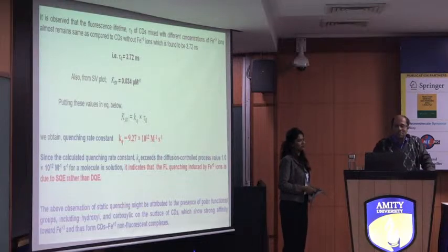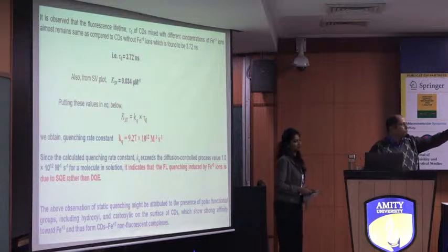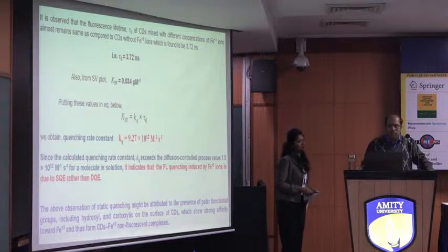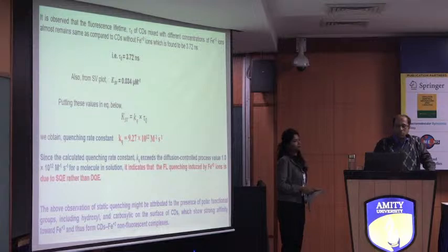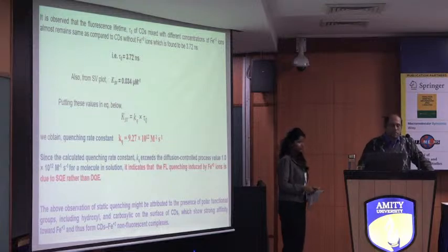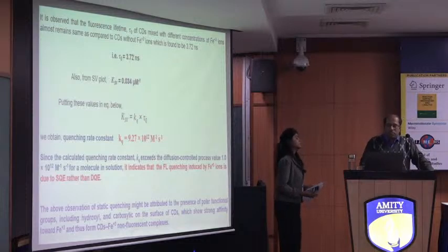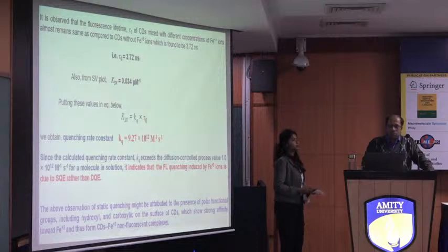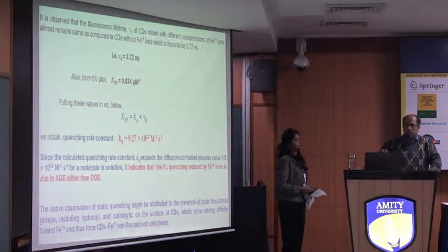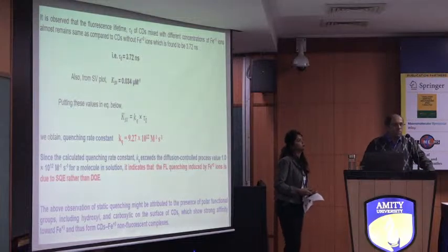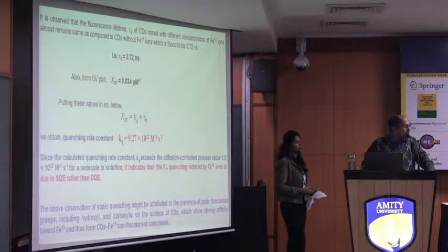So from the Stern-Volmer plot, we actually found the quenching constant to be 0.034 micromolar inverse, and from that we calculated the quenching rate constant. And since our calculated quenching rate constant was found to be more than the diffusion controlled process, which is of the order of 1 into 10 to the power of 10, we concluded that the fluorescence quenching mechanism occurring in our system is static quenching rather than dynamic quenching, and this is attributed to the presence